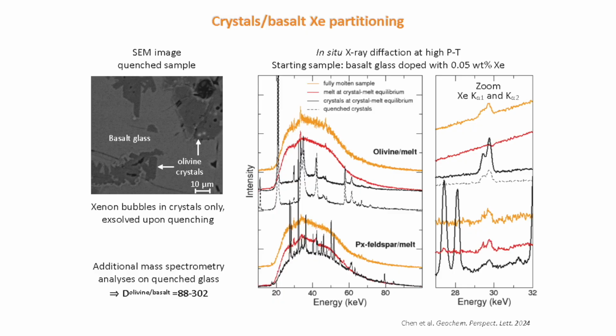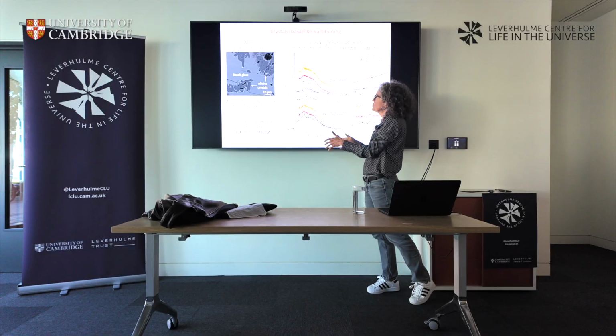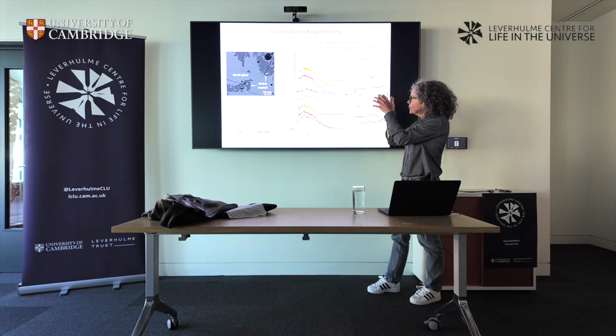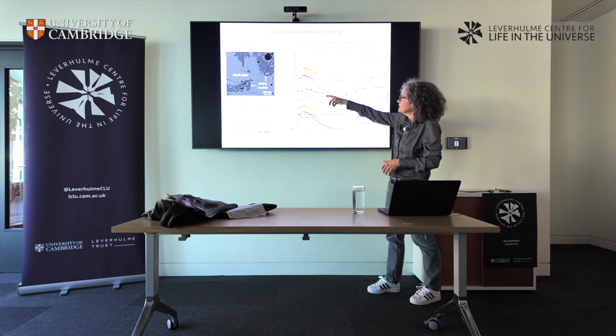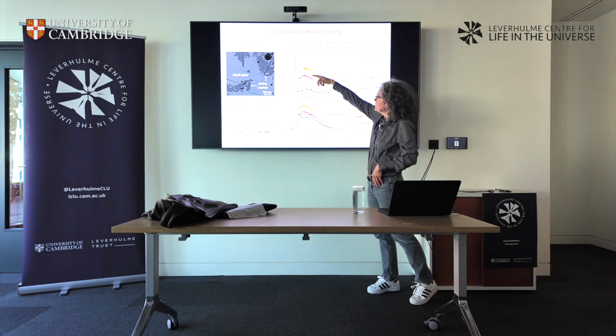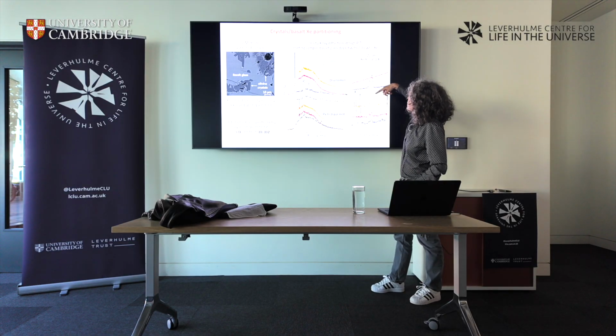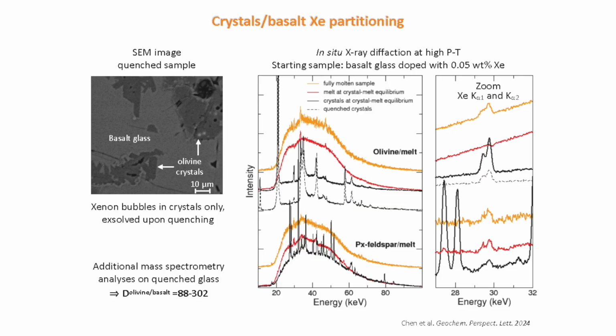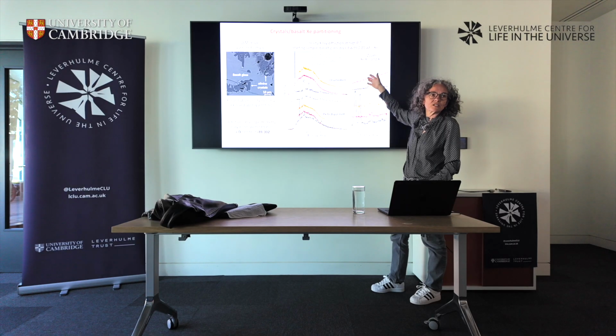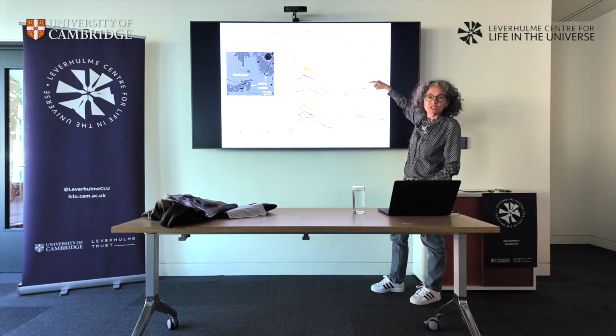You go from this to this by moving your press versus the X-ray beam position. So you can scan your sample, go in the crystal, get your data, then move in the melt and get your data there. Then you focus on the xenon zone and you measure the surface of these peaks and calculate the partition between the melt and the crystal, okay? Just looking at the surface ratio.